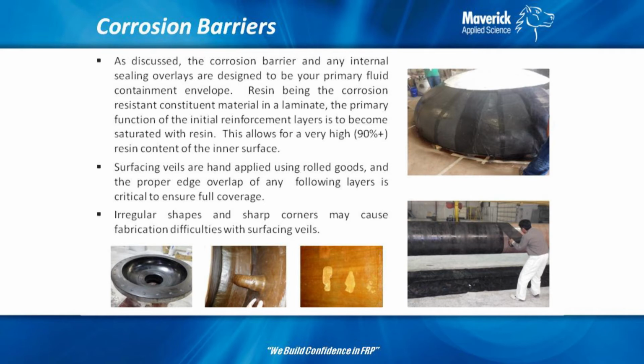When you first start putting down a corrosion barrier, again, because this is the most critical part of your vessel, this is where your vessel is going to stop leakage, is the corrosion barrier. You want to make sure everything is sealed tight and well built in the corrosion barrier. A vessel that has some air and some issues with the structural wall, there's enough structural wall typically and enough safety factor that you won't have a major issue. But if you have a small issue in your corrosion barrier, your vessel will leak eventually. So if you're doing inspections and stuff like that, you want to make sure your corrosion barriers are very tight.